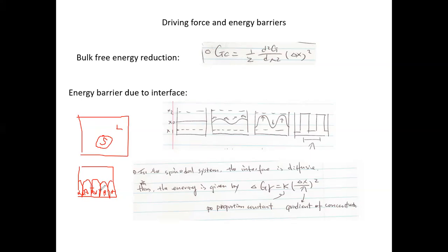Yes, right? Clearly after the separation completes, we have an interface because you have this huge distinction of composition. So in those cases, the two phases are well defined, you have an interface. But how about in the beginning? If we just start the separation, like we analyze the initial separation, you have this X naught here, and you have slightly separated composition with X naught minus and X naught plus, and in those cases, I mentioned, the interface is not quite important.